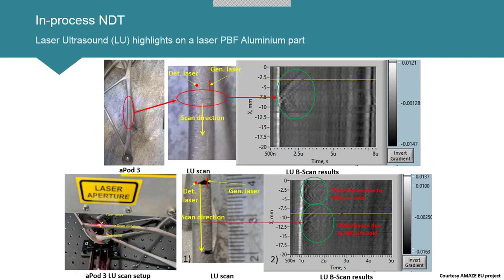So the first test on the top is a crack, or in this case, a surface defect, which is a layer defect, because that's along the build layer. So it's an opening surface crack, and we basically scan with laser ultrasound, just before and after that defect. As you can see with my mouse, this was the generation laser and this was the detection laser, and both of them move along this direction, so it's moving downwards here. This is called a B scan, which is a stack of the A scans that the ultrasound generates. And we can see the surface Rayleigh wave here very clearly, and then some of the effect of that crack.